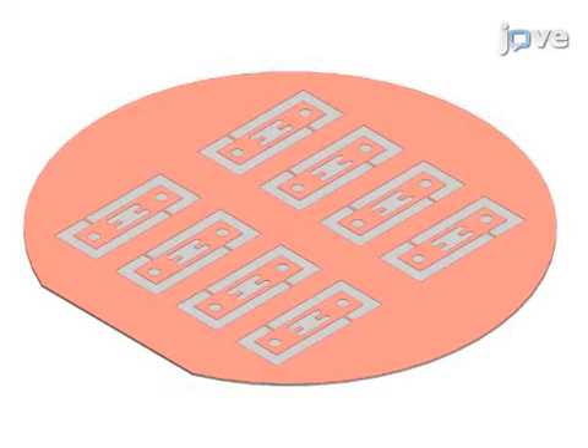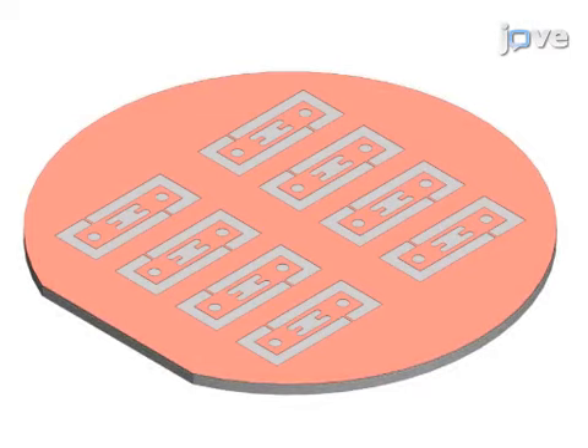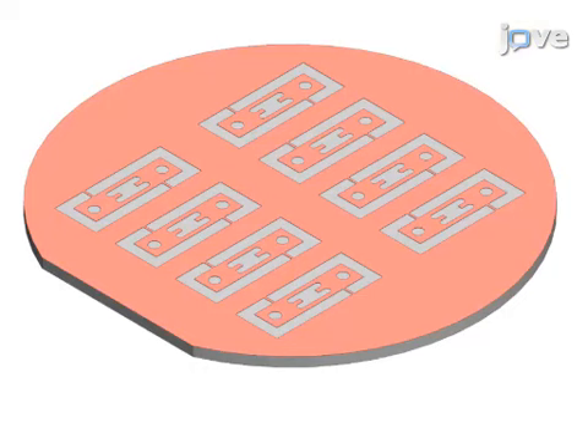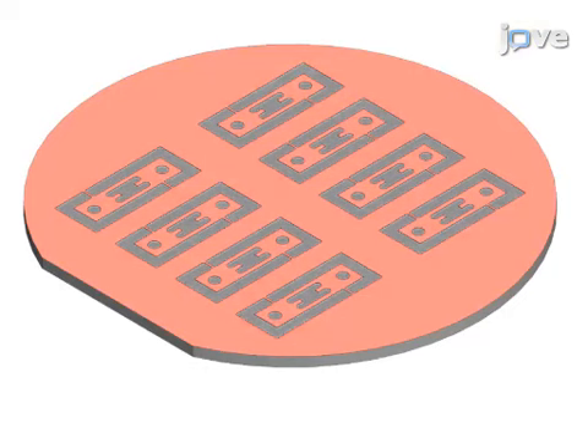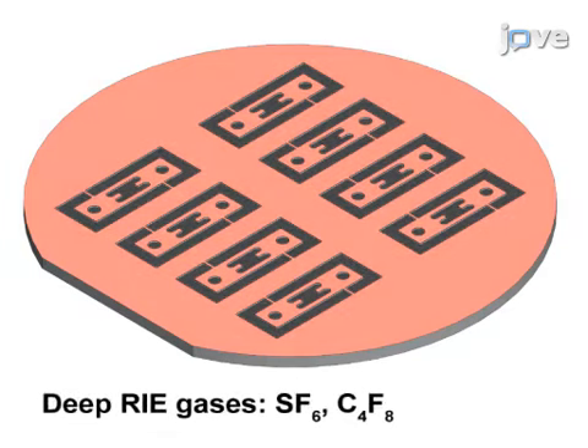Bond the patterned wafer to a 500 micron thick silicon support wafer with a low melting point temporary adhesive. Apply the adhesive uniformly to prevent excessive heating and etching damage to the patterned wafer. Then, etch through the patterned wafer with deep reactive ion etching using the Bosch process. Monitor the etching rate with a profilometer.